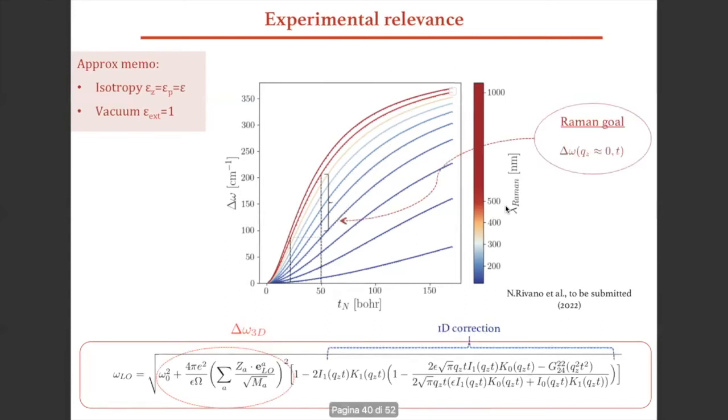So basically here, what you can see is exactly that. If we, for example, decide to use a laser which is more or less 700 nanometers in wavelength, what we can see is that the discrepancy in the dielectric shift between a nanowire which is more or less 20 Bohr in radius, and a larger one of, let's say, 50 Bohr in radius, is more or less 100 cm^-1.